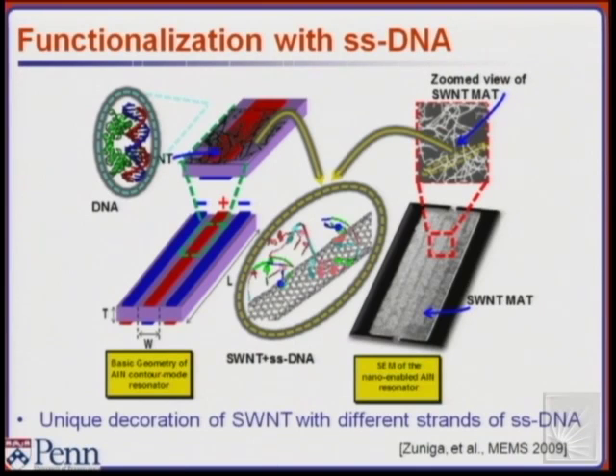In terms of functionalization, we're using a novel functionalization layer in which we've grown some nanotubes on the resonator, and we then attach single-stranded DNA to the resonator. I'm not going to focus too much on this. I'm just telling you that we have a scheme to differentiate between different types of analytes based on different strands of DNA. The sequence of the DNA can bond to different gases, to different analytes, depending on the type of strand. So you have basically an infinite library, given time and probably a good molecular dynamics simulator. You could simulate the bonding between gases and DNA and possibly predict the affinity between the two.